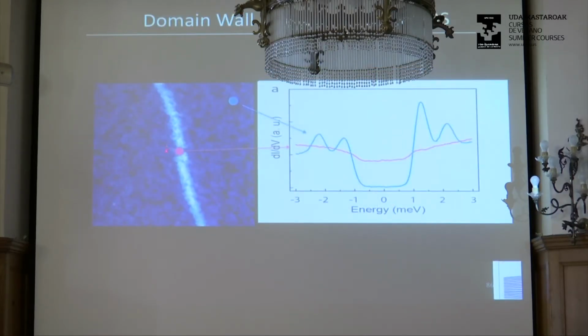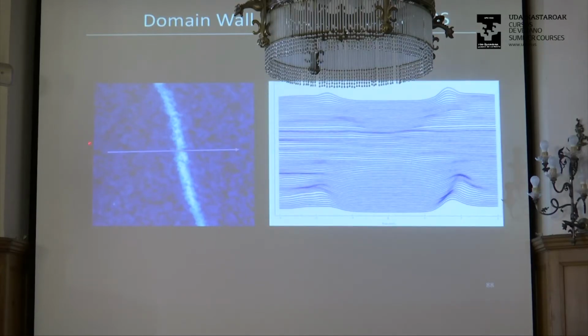Now, if you go to this domain wall, this is what you see. So far away, you see this superconducting gap. This is 0, so this is very much at 0. On top of the domain wall, you see this. So this is really already extremely interesting because, you know, I've done many different kinds of impurities in superconductors, and usually you see peaks, right? So there are two kinds of things you see. Either you see peaks inside the gap, or you see the gap itself shrinking, getting smaller or bigger. This is the first time we'd seen this kind of flat density of states, okay? So this is a line cut across this domain wall. This is sort of squished, I'm sorry about that.